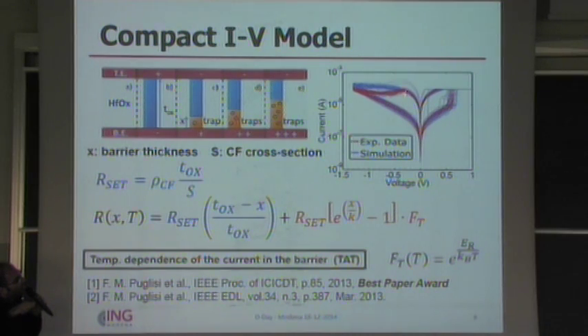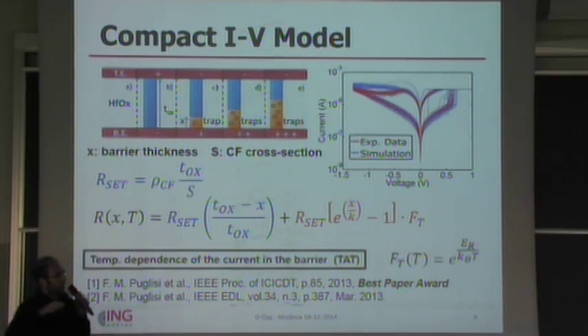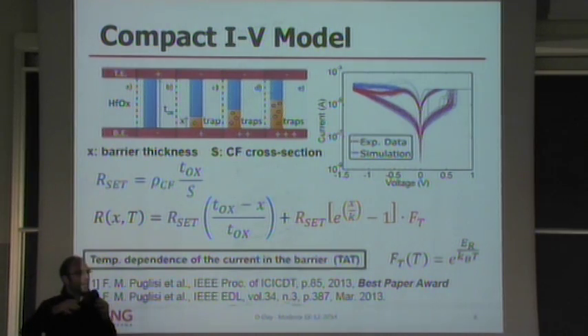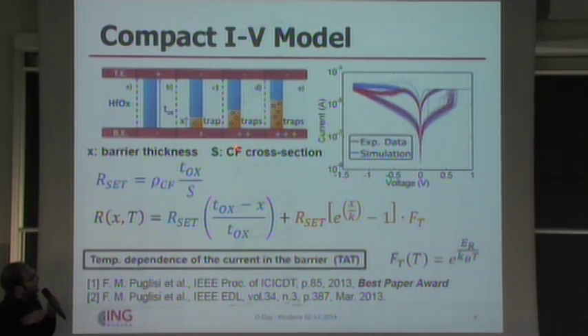When I apply a reversed polarity, DC sweep or pulse, I can break this filament here at the bottom end, and I can create a dielectric barrier. So this orange part here is not conductive anymore. Let's say it has mostly insulating properties, and the higher the absolute value of the voltage that I use during the reset process, the deeper I go this way, the thicker the dielectric barrier will be. The charge transport here is radically different because it's dominated by trap-assisted tunneling across this layer, thanks to some traps. They are oxygen vacancies, active defects in this structure, and they can carry some current. Now in this state, when I perform the set procedure, I apply a positive voltage again, and I can break this barrier again and be back in the low resistive state.